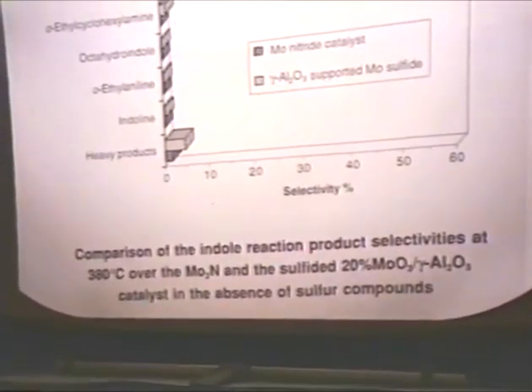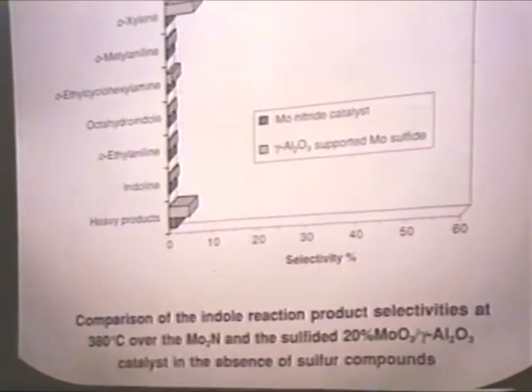Now, as I said at the beginning, we wanted to compare the behavior of the nitride catalyst with the sulfide catalyst because, in general, they're quoted in the literature as saying that nitride catalysts can be much more successful in HDN reactions because of their low hydrogen consumption, because they don't end up saturating all the hydrocarbons. Now, we wanted to make some comparison, and really the best comparison we thought would be the molybdenum nitride with the sulfided molybdenum catalyst. This is a supported catalyst. Now, in this comparison, all parameters are kept constant except the amount of catalyst.